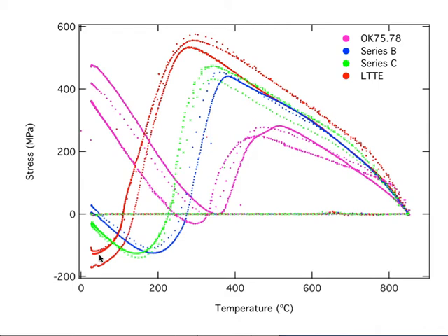Now of course these are still quite simple tests, and what you need to do is to prove it for a weld metal, and you make a weld and then you measure the residual stress in there. Now, what sort of diffraction technique could I use to do that? Because these are not small objects. X-rays can penetrate a few millimeters, but I want to look at the stress distribution in something that's centimeters big. Neutron diffraction, okay?